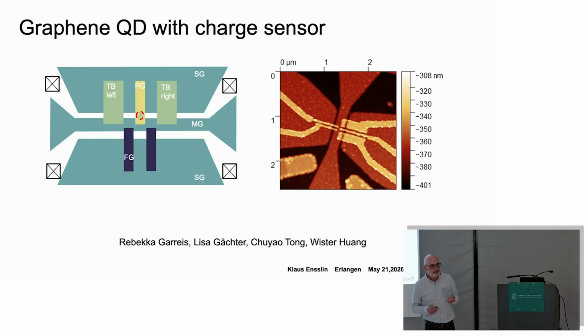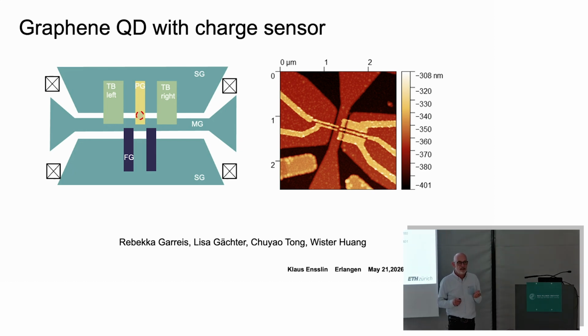Okay, now let's try to measure the lifetime of these states, right? So far I've shown you ground states of various electron occupations, but now you would like to build something and understand how long a state actually lives. So what you see here is a more complicated schematic. The green gates are our old split gates, and they are used so that you have no carriers below and a gapped region. So you're left with the 2 white channels here where the current can flow. The top channel is where you build your quantum dot as before, and in the bottom channel you can also build a quantum dot or a constriction or whatever, but it works as a charge sensor to what's happening on the other side. This idea of having a charge sensor has been done in gallium arsenide, silicon, germanium, and so forth, and it's the same thing here. You basically have 2 quantum devices. One is the quantum device that you would like to understand.